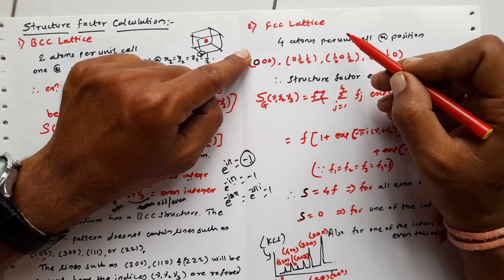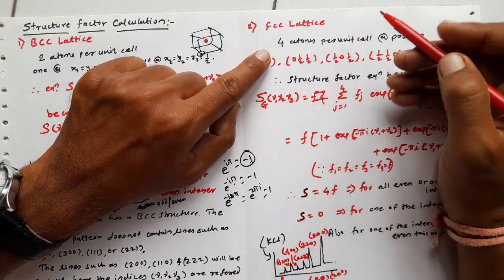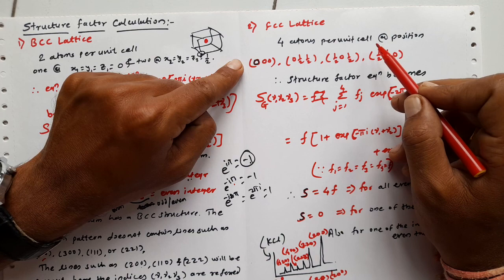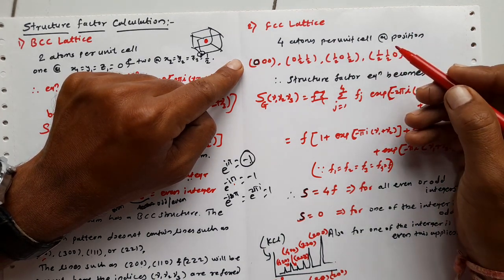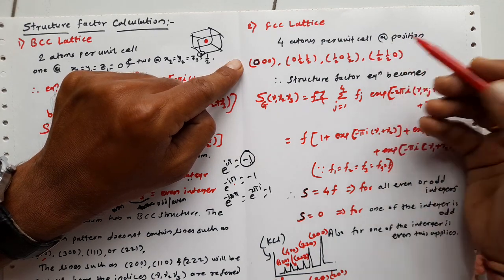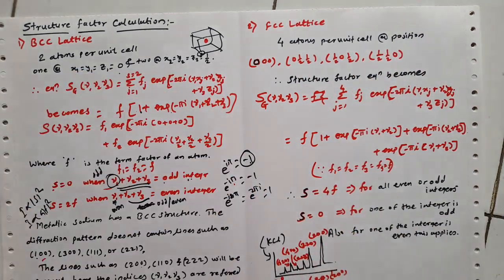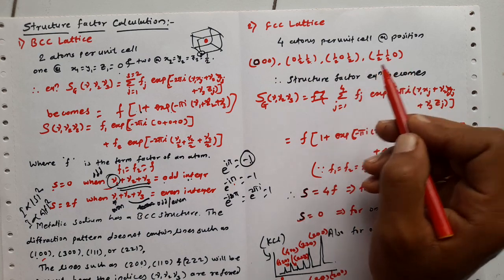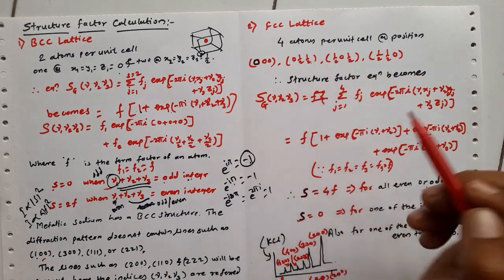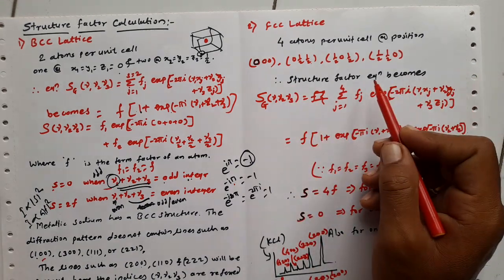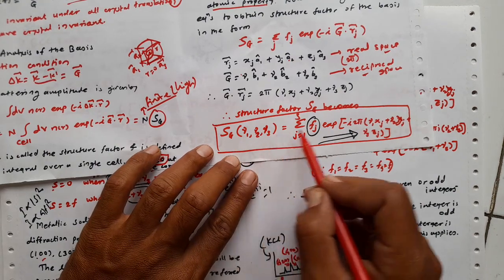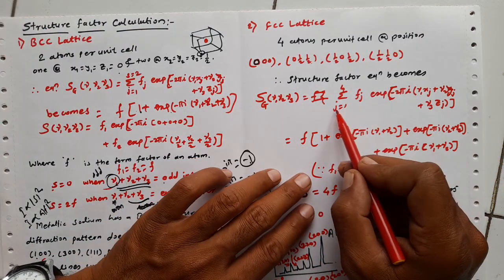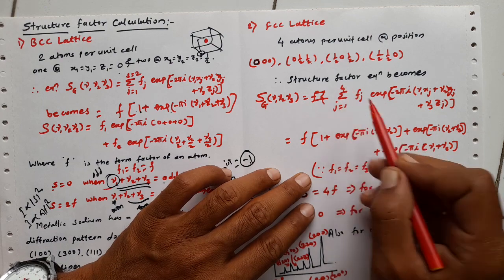Another example is the FCC lattice. In the FCC lattice there are four atoms per unit cell — one contribution from the corners and three atoms contributing from the six faces, half from each face. The four atoms and their positions in the unit cell are: (0,0,0), (0, 1/2, 1/2), (1/2, 0, 1/2), and (1/2, 1/2, 0). The structure factor summation now runs from j=1 to 4, so S=4.